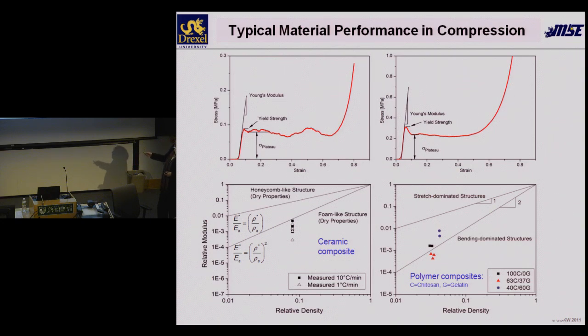We looked at the next level of hierarchy — the cell wall structure and properties. Using the same recipe and composition but different particle sizes, we get very different mechanical performance. You can tune properties through the sheer choice of particle size. The least strong is the small particle material; the best is the bimodal distribution, and 10 degrees per minute freezing rate gives the best result because it has a finer structure. The small particle material failed in a brittle way, whereas the large particle material had a much more ductile performance. We believe this is because the large particles are strung on a polymer string, allowing more plastic behavior since the glue plays a more important role.